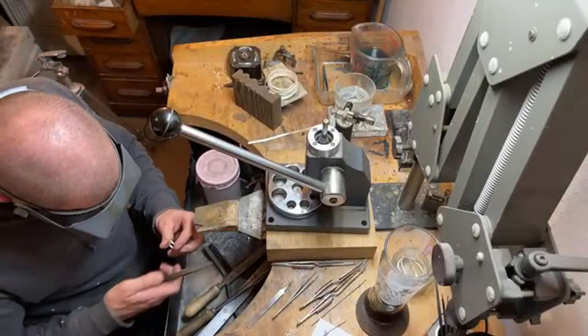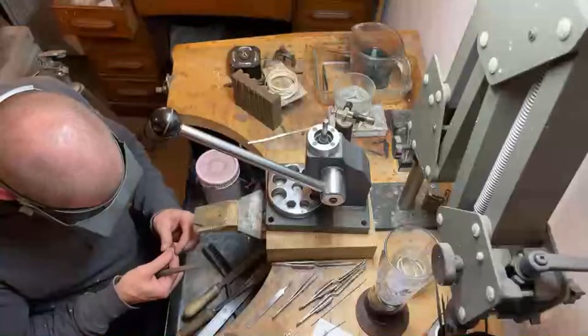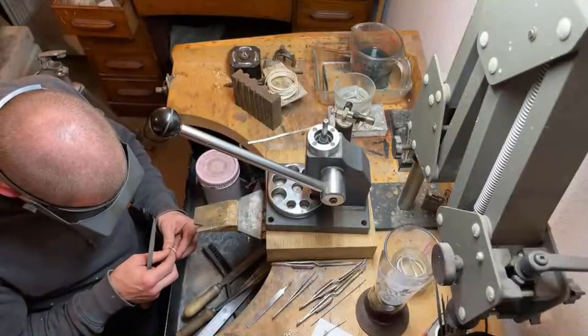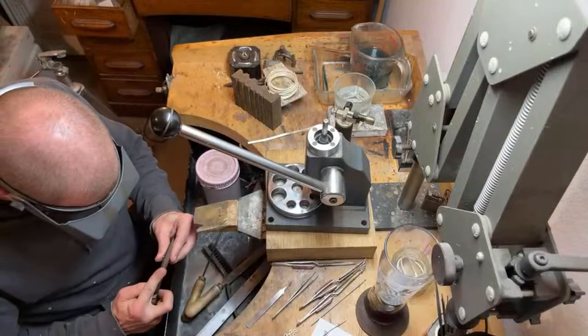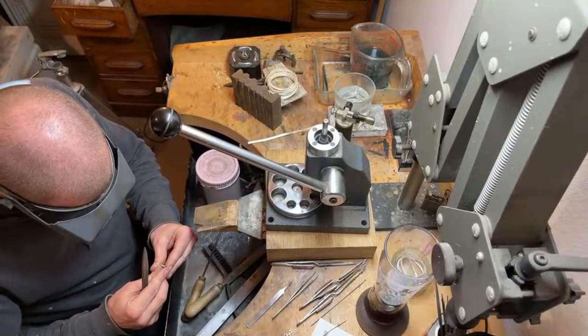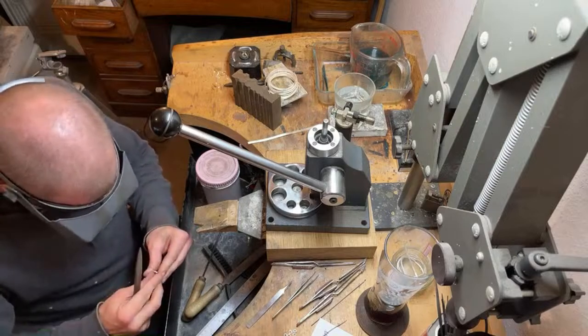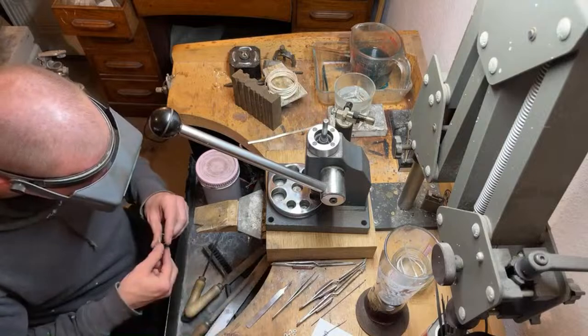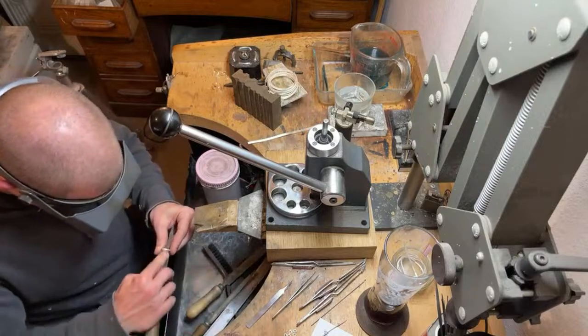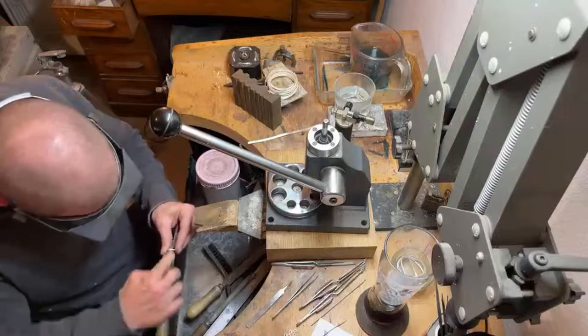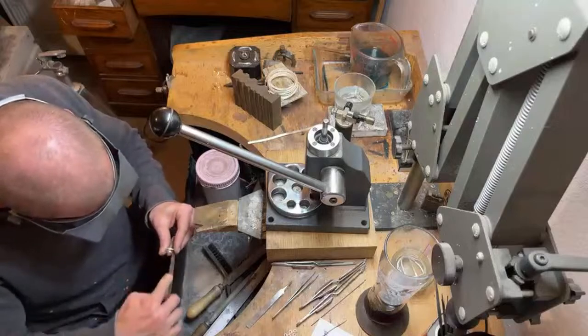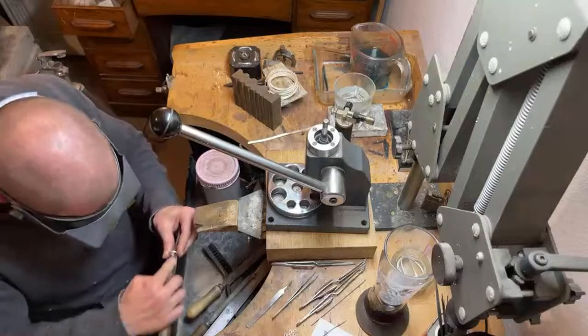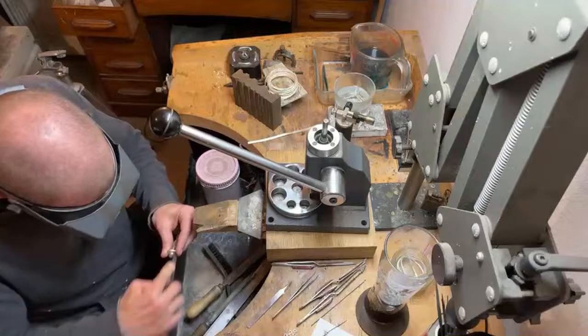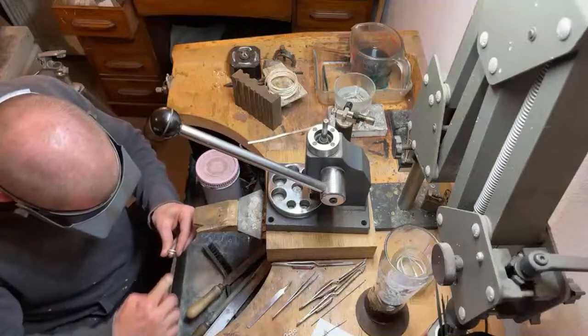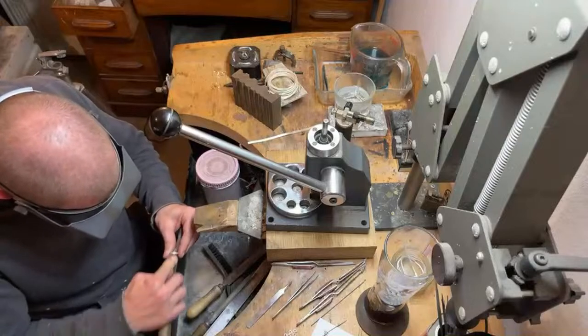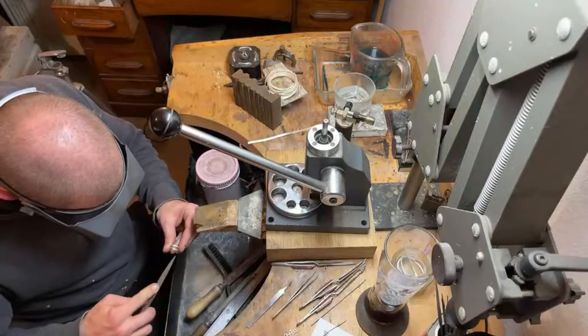Yeah, all the excess solder on the inside again. This one actually, there might be a spot of porosity in the joint there, but it was just the seam. I've learned now, if you get porosity in the solder joint, just redo it. Don't try and file it out, don't try and polish it out. Just solder it again before you mess around.